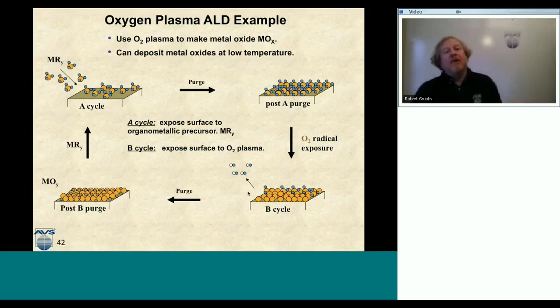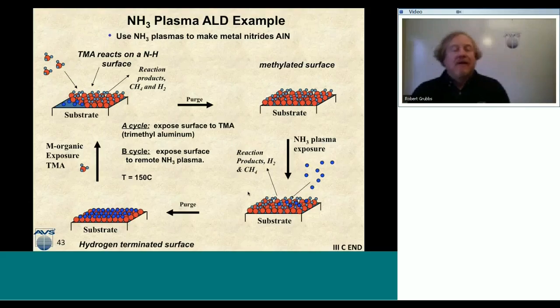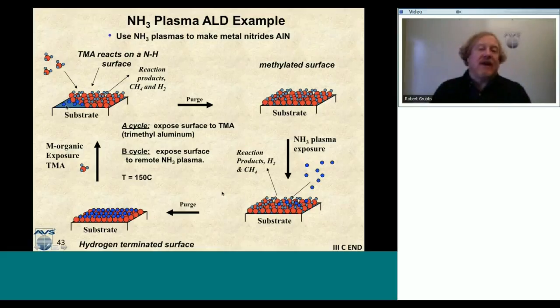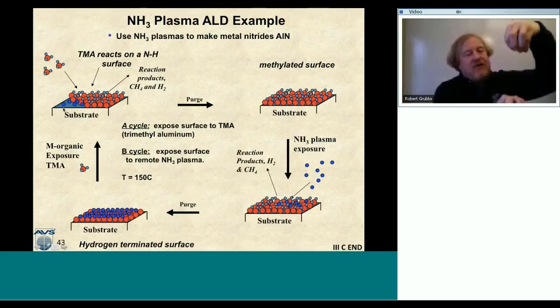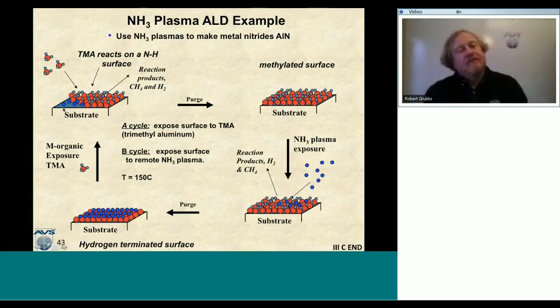Another example would be ammonia plasma. Here we can use this to make aluminum nitride at 150 degrees C. So here I have a surface, and I've got this NH on the surface, this nitrogen hydrogen, that's my reactive handle. I come in with trimethyl aluminum. It'll react with that NH bond and make methane and hydrogen gas. And so now I've got this methyl terminated aluminum surface right here.